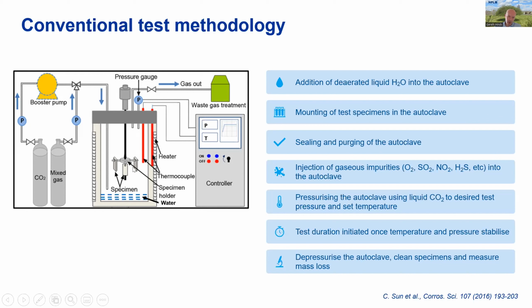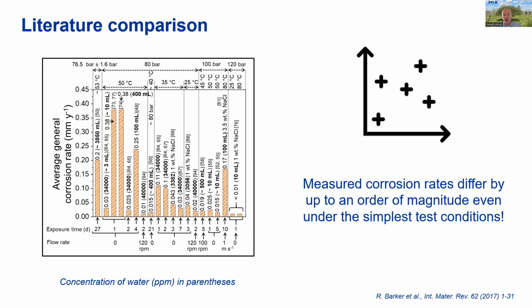The specimens are removed carefully, they're cleaned, and then the mass of the specimens is carefully recorded. And then by comparing them with the initial mass, you can determine the amount of mass loss due to corrosion that has occurred during the test. So that's a typical corrosion test. Some of the details of the methodology vary, but most of these things that we've listed here are common to all methodologies. Now, the problem arises when you look at the literature, and this was quite surprising to us.